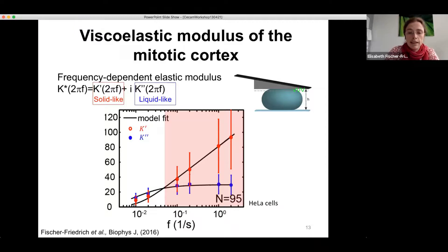But we then have also a characteristic transition time scale, tau, where the two curves are crossing over and a lower frequency regime where the loss modulus starts to dominate. That means the cortex starts to behave more and more liquid-like. This is actually also what is kind of expected because we know that the cortex undergoes turnover. So it depolymerizes and re-polymerizes all the time. That means over time the cortex will forget about a certain reference shape that it had in the past and because it repolymerizes then in a new shape over time, like after a deformation.